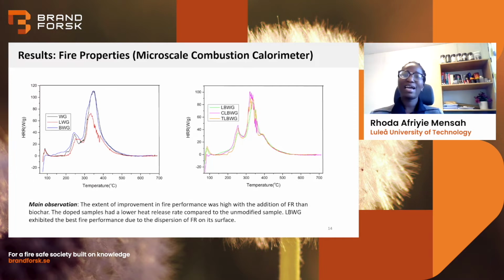If we consider the doped samples on the right, we see that the peak heat release rate recorded actually falls between that of the LWG and the WG, neat wheat gluten sample. And if we take a critical look, we see that the green line, which is for the dry mix, LBWG, had the best fire performance. That means it had the lowest peak heat release rate.